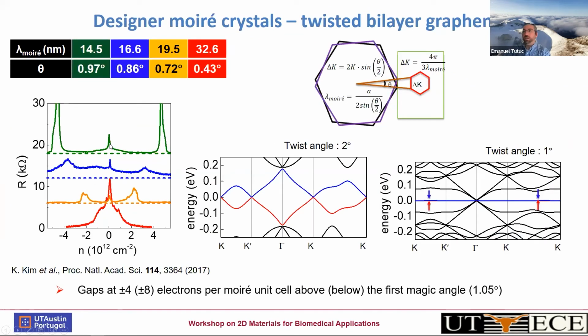I mentioned initially. So if we had a single layer, we would see a charge neutrality point when the sample is undoped, and then the conductance would become high. But then there would be locations where the resistance goes up very sharply and there is an insulator. And that is the location where we have filled out a Brillouin zone of this moiré pattern. Remember, in real space, we have a large wavelength. Therefore, in momentum space, the Brillouin zone is very small, and therefore we can fill it up electrostatically with electrons.